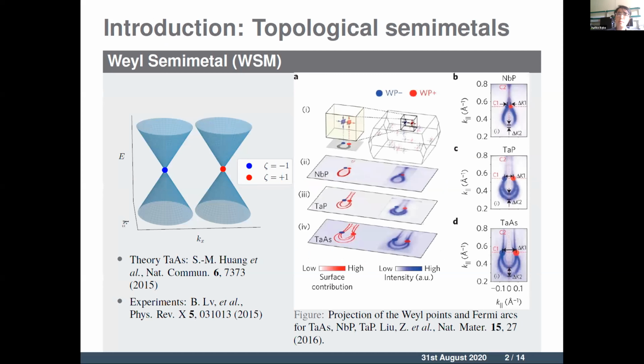Then let's start by introducing in more detail the 3D topological semimetals we are interested in and their phenomenology, namely Dirac and Weyl semimetals. In these materials, the conduction and valence bands touch at isolated points, leading to a gapless dispersion alongside an absence of Fermi surface. The touching points are called Weyl and Dirac points, and between these points, arced surface states appear, protected by topology and symmetry. In these surface states and their properties resides a great part of the interest in these materials.